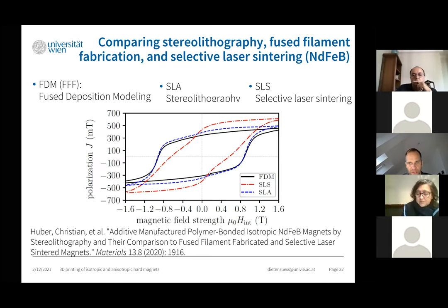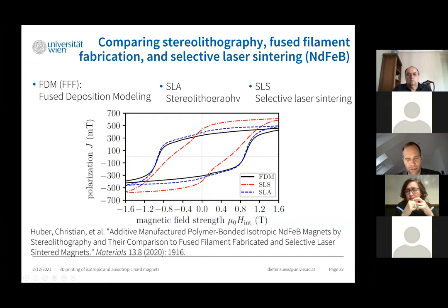If you look at the magnetic properties, as expected, stereolithography and fused deposition modeling have very similar hysteresis loops, because both are kind of polymer bonded magnets where we have a high degree of non-magnetic material in the final magnet. A little bit higher remanence has the stereolithography magnet. And the selective laser sintered magnet has the highest remanence, of course, because it has no polymer inside the magnet and it's a fully dense metallic structure.